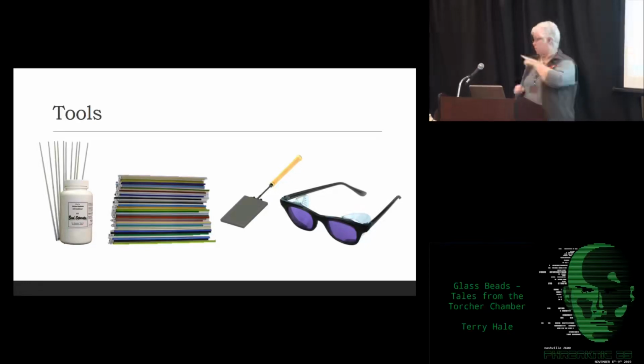The glass rods, which just went around here, and then the paddle over there is graphite. When we're shaping and making long skinny beads, we roll the glass. You don't want a tool that's going to suck the heat out of the glass. If you use brass, it's going to cool it off too fast and put stress in it. Graphite tends to not soak up the heat so quickly, and you have more working time.